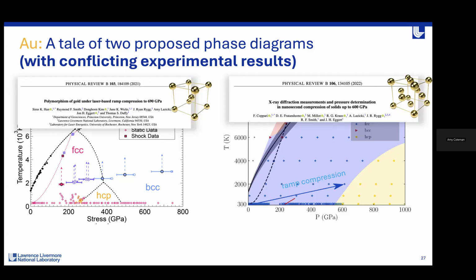One of the findings was that if in your target package you have a diamond sandwich - a diamond layer on either side of your sample - there can be quite a bit of excess heating. When we look at this paper, the target package that was used, some of them did indeed have these diamond sandwiches. So one thought we had was, well, perhaps these results were driven by ramp compression, but actually they're representing something at significantly higher temperature. Maybe this BCC phase exists, but because of the diamond sandwich in the target package, it exists at much higher temperature.